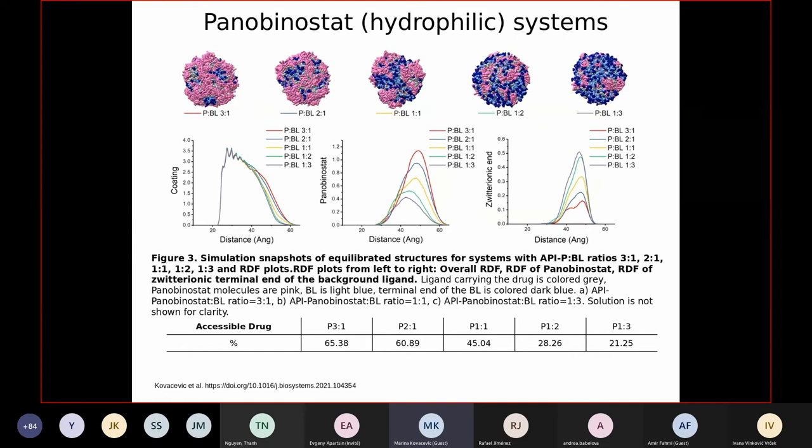Comparing with quinolinol system, we can observe the same trend. So, as we increase the initial concentration of the drug, the more of it appears on the surface. And due to hydrophilicity of this drug, the higher amount is available comparing to quinolinol systems.